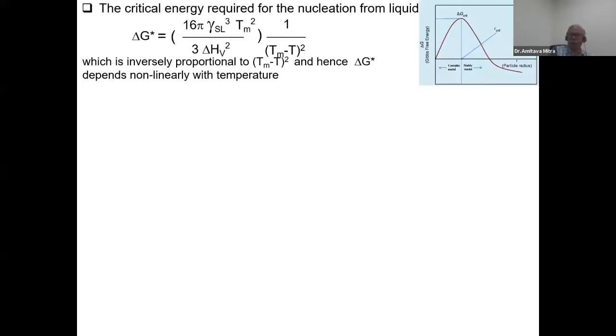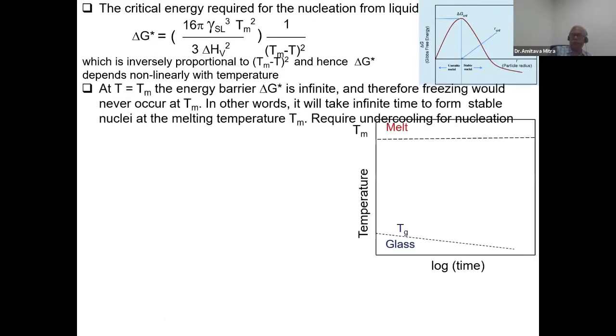So if we plot this, it gives a curve like that. At this stage, the nucleation for crystallization starts at this critical free energy, which depends on Tm minus T whole square. This is the critical free energy at which the nucleation for crystallization starts.